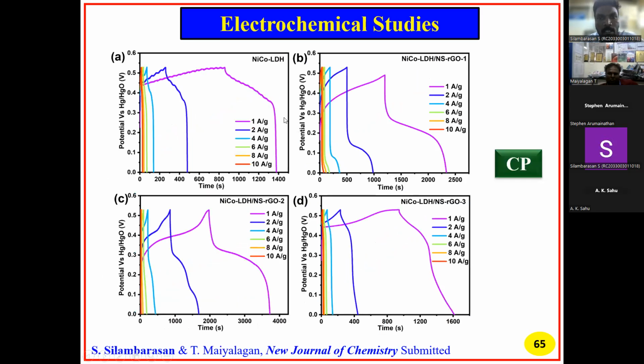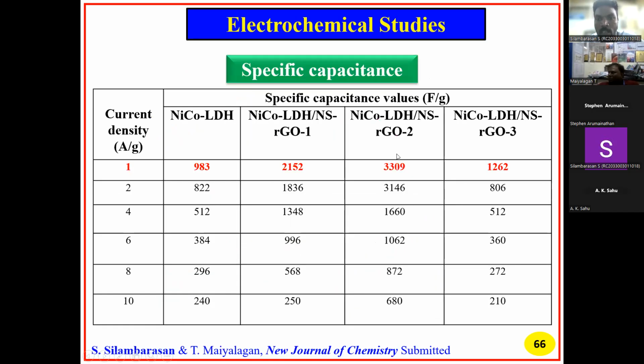Next, the charge and discharge. The current density from 1 ampere to 10 ampere per gram we measured here. And overall, sample 2 has the longer discharging time, so it gives more performance compared to the other samples. So the performance of sample 2 is 3,309 farad per gram at 1 ampere per gram current density, and compared to the other samples it gives more performance.